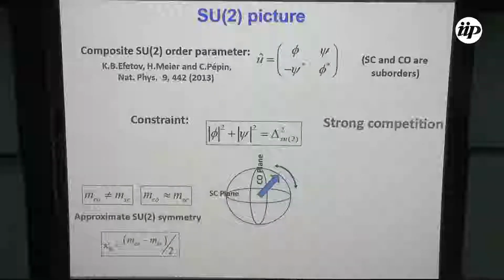If we make the masses different, but not so much that we break the symmetry absolutely, so the masses are different but very close to each other, we have an approximate symmetry. But by doing this, we have introduced an energy cost for this pseudo-spin to go from the superconducting plane to the charge order plane, and this energy cost is given by the difference of the two masses.